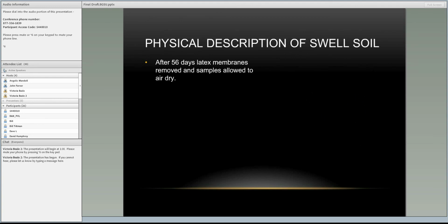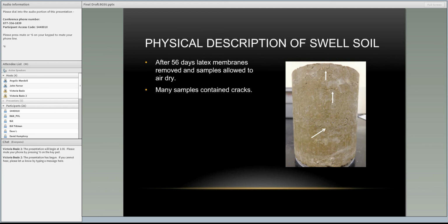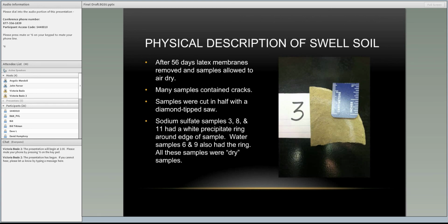And another thing we noted was that the sodium sulfate samples 3, 8, and 11 had a white precipitate ring around the bottom of the sample. This particular sample has two, one that's a little bit larger than the other. The small one's like a millimeter, and the other one maybe half a centimeter. And we noticed these rings on several of the samples. On the water samples, we noticed them on 6 and 9. And another thing to point out was that the only samples that had these rings were dry samples. None of the wet samples had these.